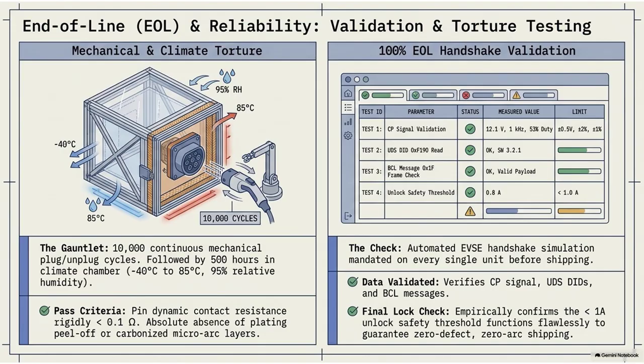But even that pales in comparison to the mechanical torture, the 10-year weather and wear test. Oh, this one is rough. This is the one that really proves how over-engineered these systems have to be. We talked about fretting and microarc oxidation wearing away the silver plating. To validate the lifespan of the physical port, they take a physical charging plug and socket and they hook it up to a robotic arm. The robot physically inserts and removes the heavy plug 10,000 times. 10,000 violent insertions. This accelerates a decade of physical friction. It guarantees that the wiping action grinds away at the metal, simulating the deepest possible mechanical wear.